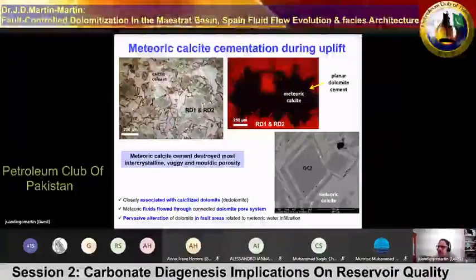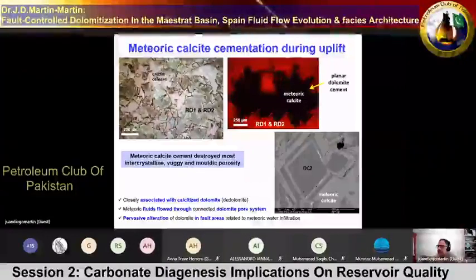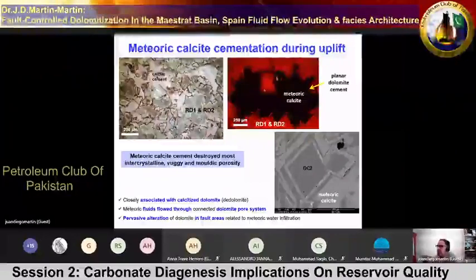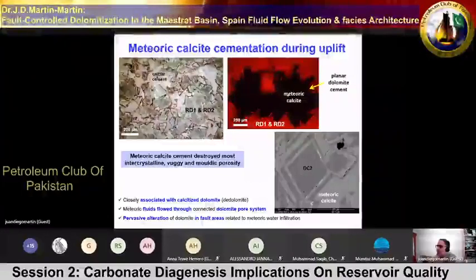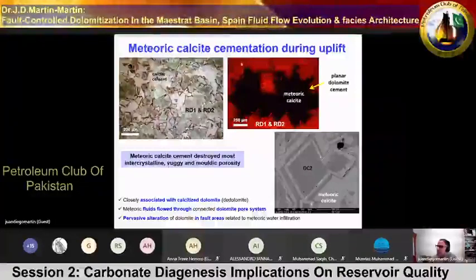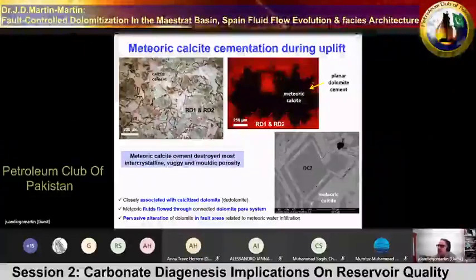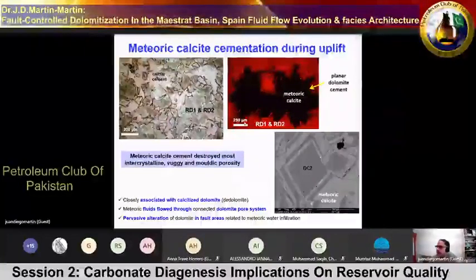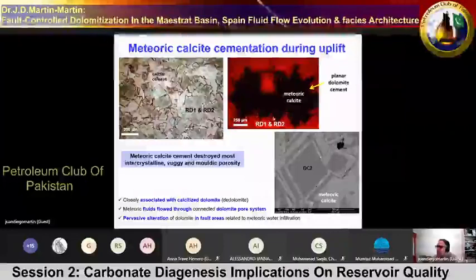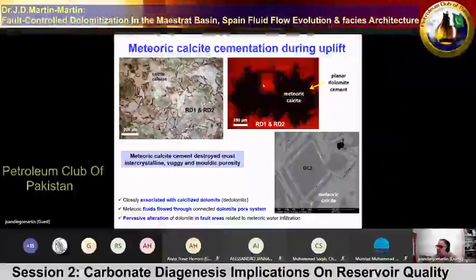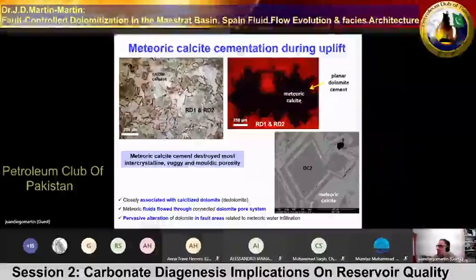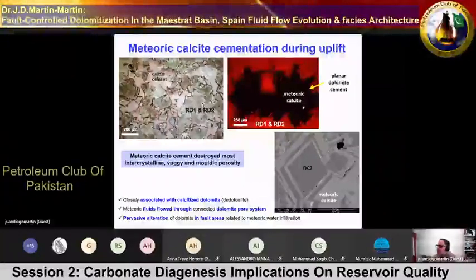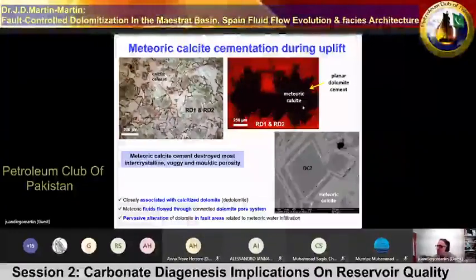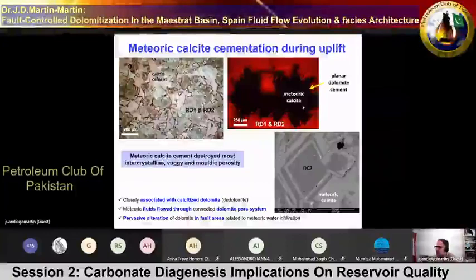Calcite completely destroyed this porosity. We have a cathodoluminescence colour. We have the red color typical of the dolomite. We have the dolomite cement 2, which is the over-dolomitization, and still we have a pore that has been filled with this meteoric calcite, typical meteoric calcite with a black cathodoluminescence signature.